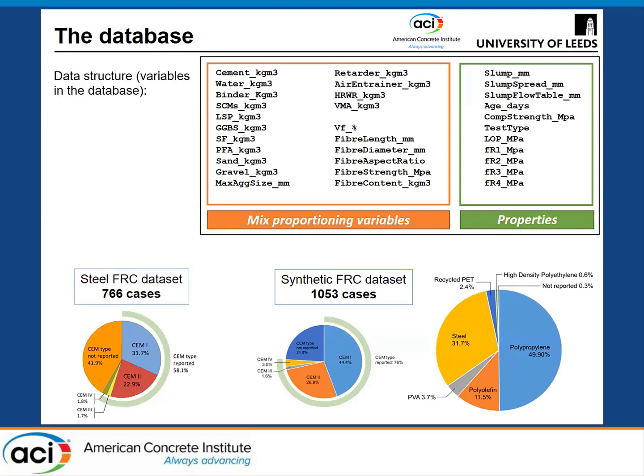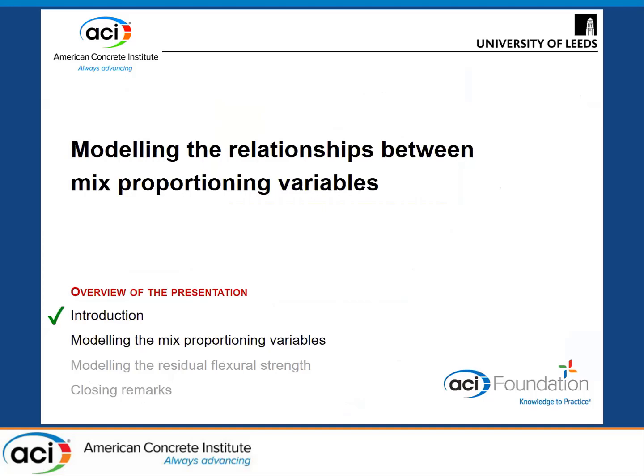And then for each of the cases, for each of the entries that we have in that database, we also have the variables related to properties. So we have the slump, we have the compressive strength, the residual flexural strength parameters. And the database is organized in 2 data sets. So one is for steel fiber reinforced concrete mixes, and the other one is for synthetic FRC mixes. So as you can see here, we have nearly about 2,000 cases, almost complete cases of information regarding different mixes and the properties. So there is a lot of variability going on in there. And that's when you can start capitalizing on that variability to extract information.